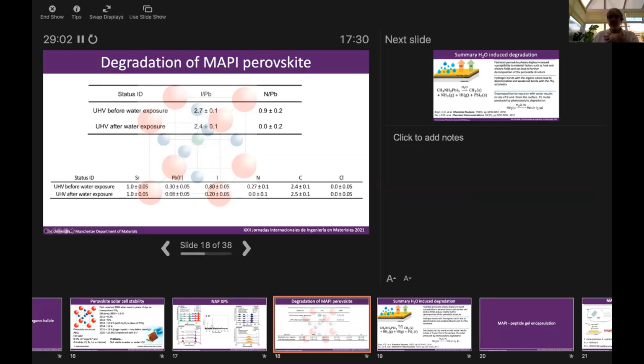We can also look at the composition of all the other elements in there before and after. So we've normalized this to silicon. We see a lead to iodine ratio here of about 1 to 3, as you would expect. Here, lead to nitrogen of 1 to 1, and lead to carbon is quite high here because we've got some contamination in the system.